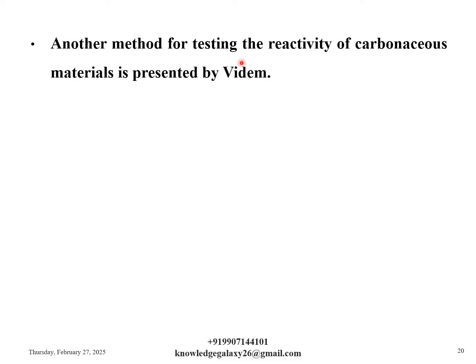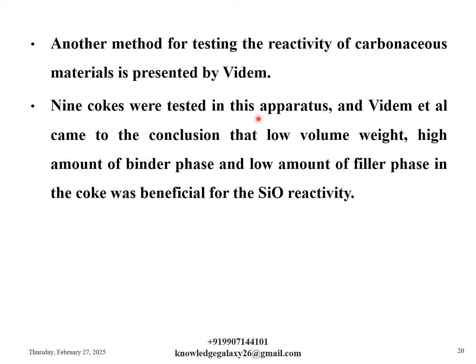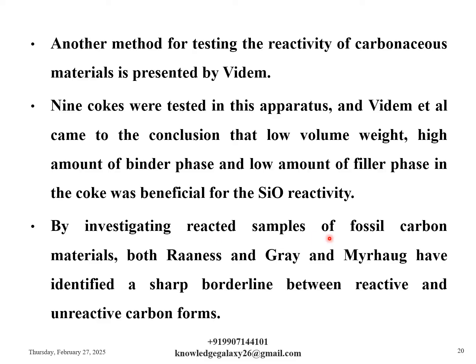Another method for testing the reactivity of carbonaceous materials is presented by Videm. 9 cokes were tested in this apparatus and Videm et al. came to the conclusion that low volume weight, high amount of binder phase and low amount of filler phase in the coke was beneficial for the SiO reactivity. By investigating reacted samples of fossil carbon materials, both Raaness and Gray and Myrhaug have identified a sharp borderline between reactive and unreactive carbon forms.